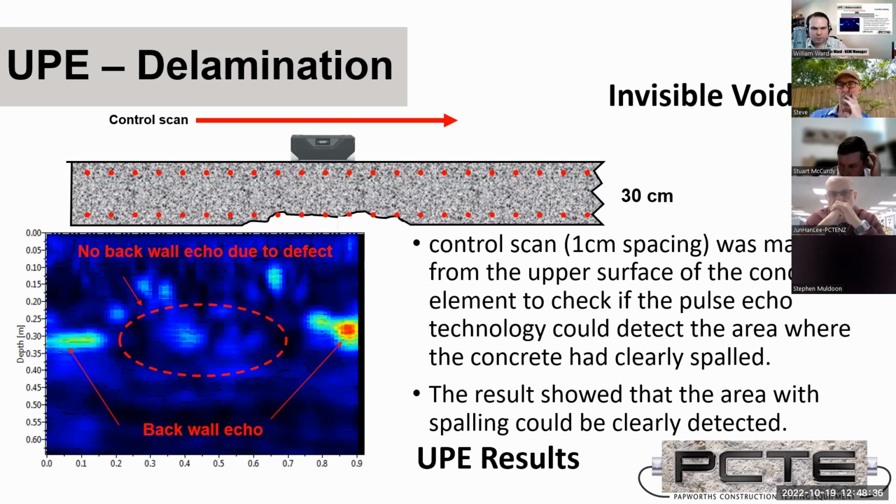So summarizing, GPR is not my favorite tool for finding spalling and delamination. You would need a very open area, so much so you'd probably bounce on it physically. It's so visibly popped up out of the concrete to find with radar. Whereas even a slight separation will be sensitive with an ultrasonic tool or impact echo tool. And also the interpretation of these is either positive, finding reduction in thickness, finding strong reflections at the level of the delamination, or in some cases negative, signal disappearing where signals should be available, like a thickness measurement on a slab.